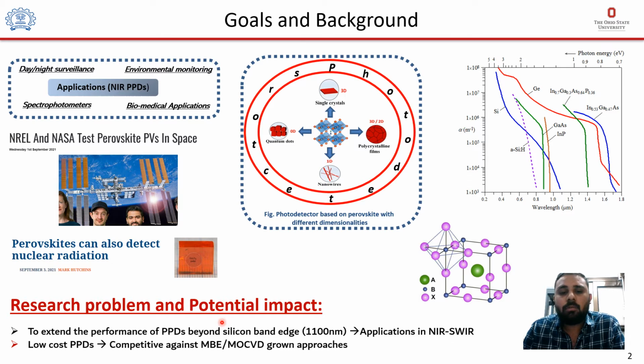Our research problem is to extend the performance of the perovskite-based photodetectors beyond the silicon band edge, which is at 1100 nanometer. Currently, we have our baseline device at 820 nanometer. Second, we are following a low-cost fabrication process, which is spin coating, which is highly competitive against the high-cost MBE and MOCVD grown approaches.